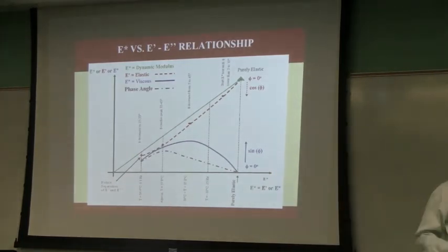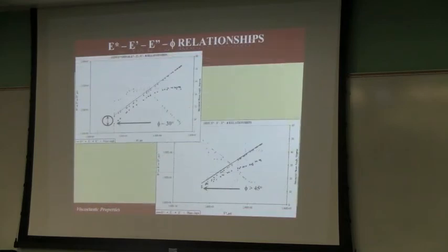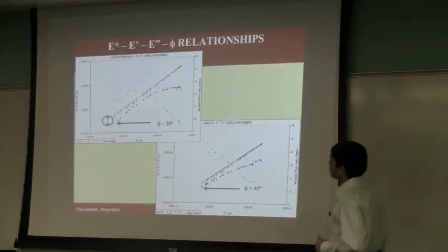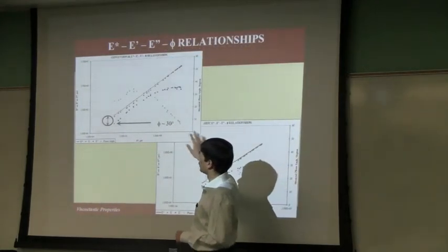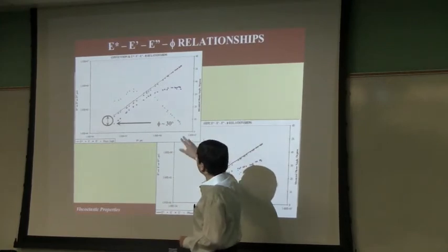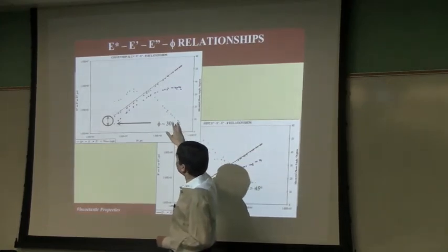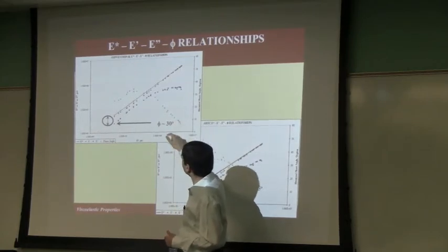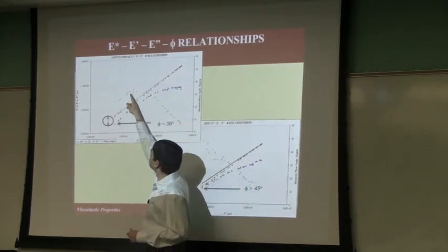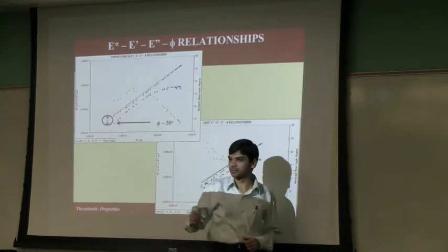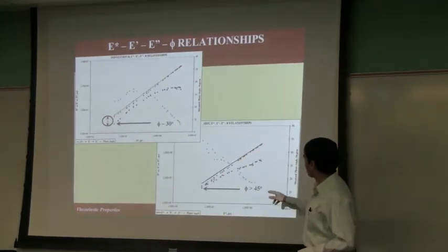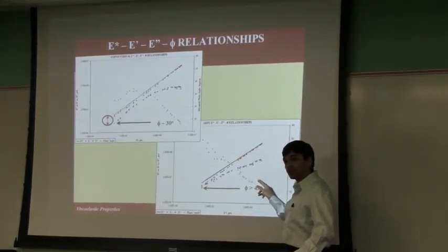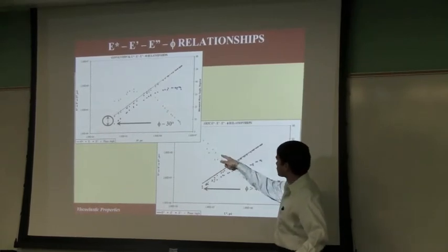So if this is theory, here it is. This is a conventional mix versus an asphalt rubber. The value of phase angle that you see here, that's in green here. It starts to increase and reaches a peak and then drops, that you have seen before. Asphalt rubber mix, it increases and there is no drop.